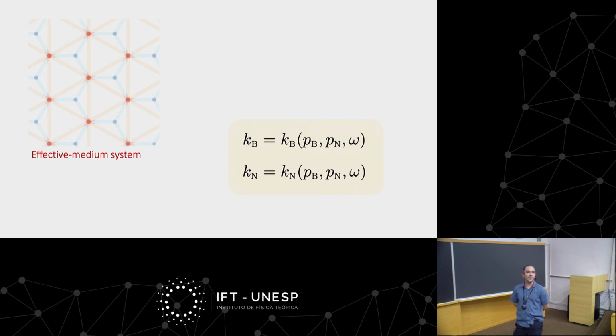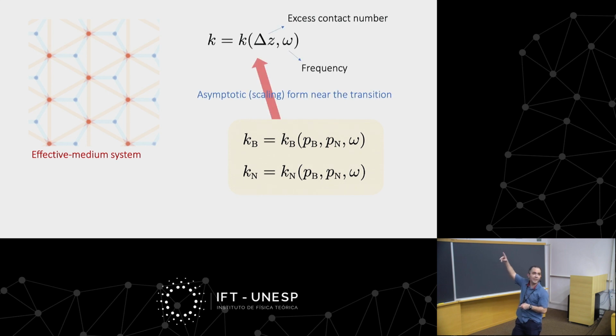Now, I've shown you this before. You have, in your effective medium system, these effective spring constants that in general depend on PB and PN and omega. And you can work out the equations and get some asymptotic solution near the transition for these effective spring constants that will depend in general on some excess contact number and frequency. And from this, go ahead, Pablo.